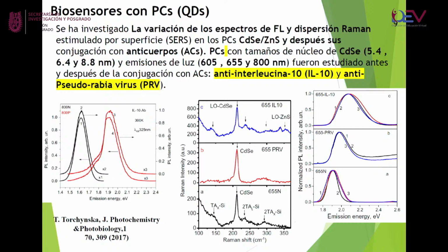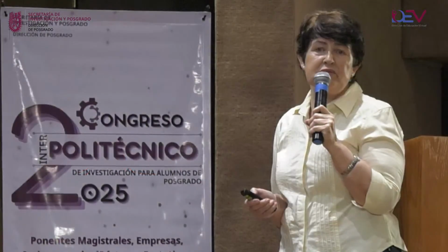Influence of quantum dots on photoluminescence spectra and Raman scattering. In this central figure, you could see Raman scattering spectra. Also, you could see that the intensity of the Raman peak increased very much compared with the 605, 655, and 800 dots. It increased very much in the process of bioconjugation. This effect has the name surface-enhanced Raman scattering.